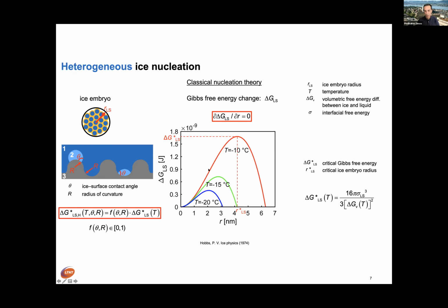Now, all that is for homogeneous nucleation, without the influence of a foreign body in the water. If you have heterogeneous nucleation, like the one I show here, that is, if your liquid water is in contact with a foreign substance like the surface, this barrier is, according to nucleation theory, given by an equation similar to the homogeneous case, times an interesting function that is very long. I didn't write it out. That function depends on the geometry of the texture of the surface, where r is not the RMS but the radius of curvature of your texture, and theta is the wetting angle. Therefore both the architecture of the surface as well as wetting properties play a role in determining this f. And of course, this f has by its definition a value between 0 and 1.